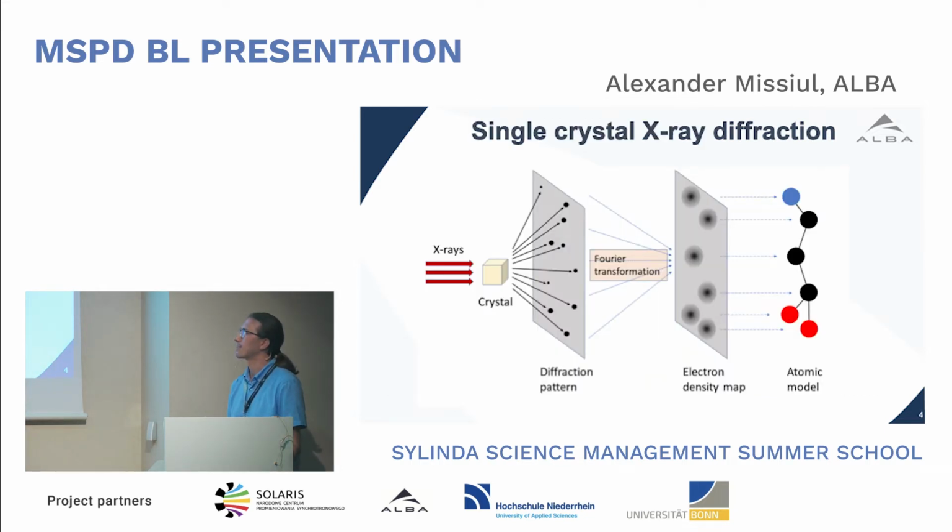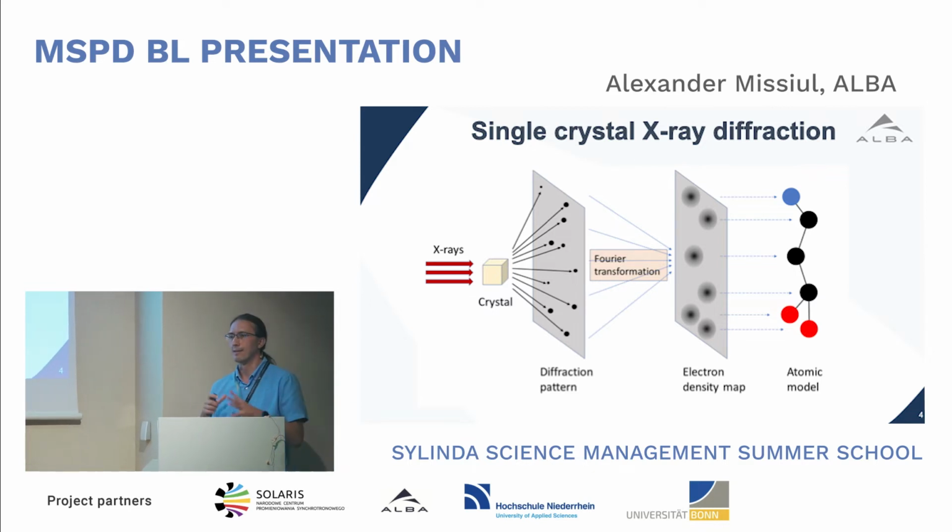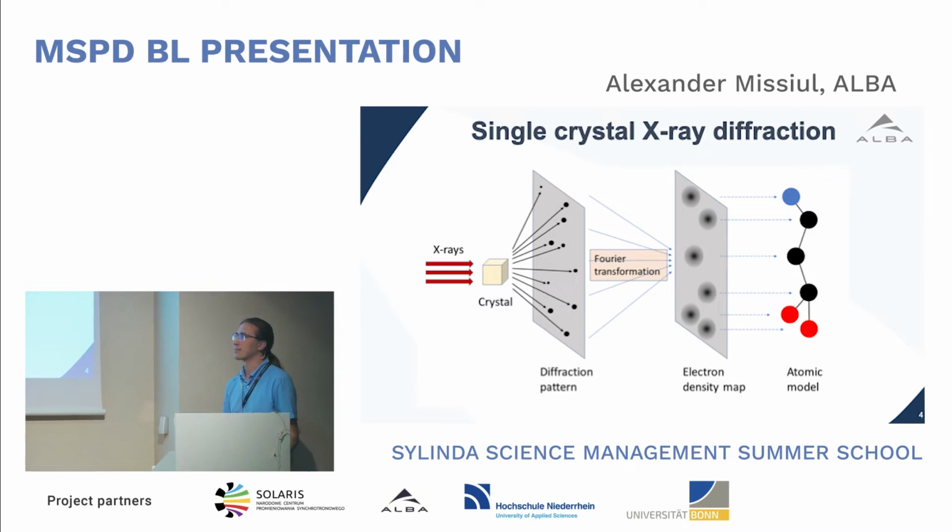So we irradiate the crystal by X-rays, we create the same kind of pattern with some bright spots where the beam passes, and after that we can go back using Fourier transformation of this picture, and we get the distribution of electronic density in space, and from this distribution of electronic density we can reconstruct the molecule, the arrangement of ions in some inorganic material and so on.